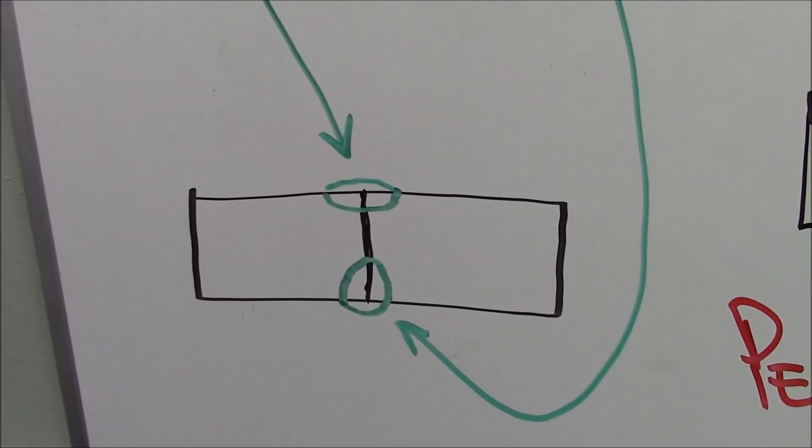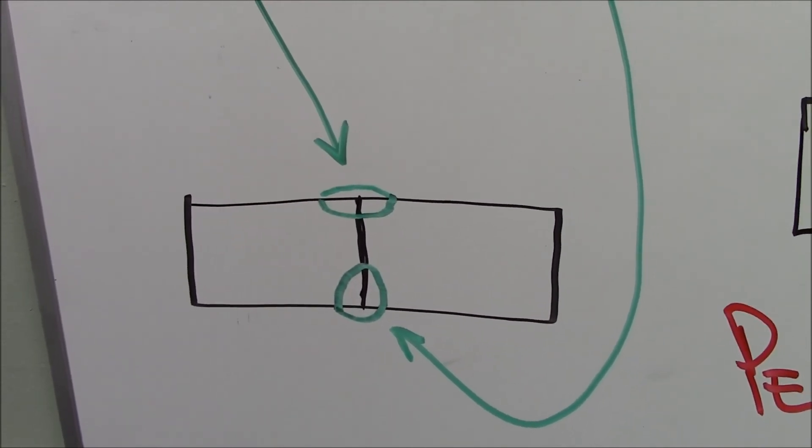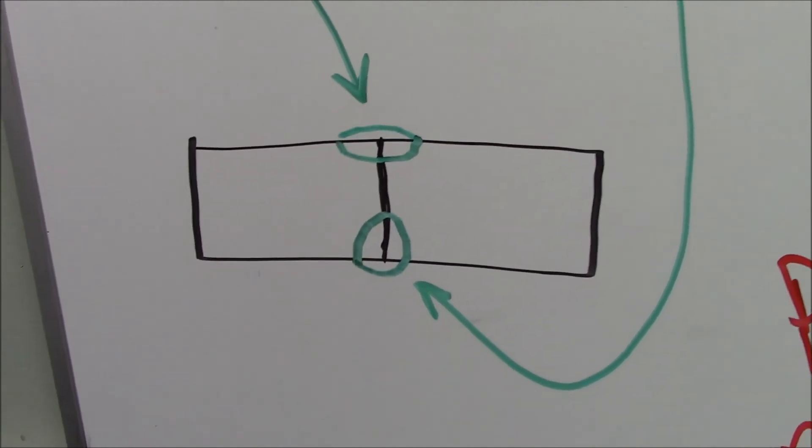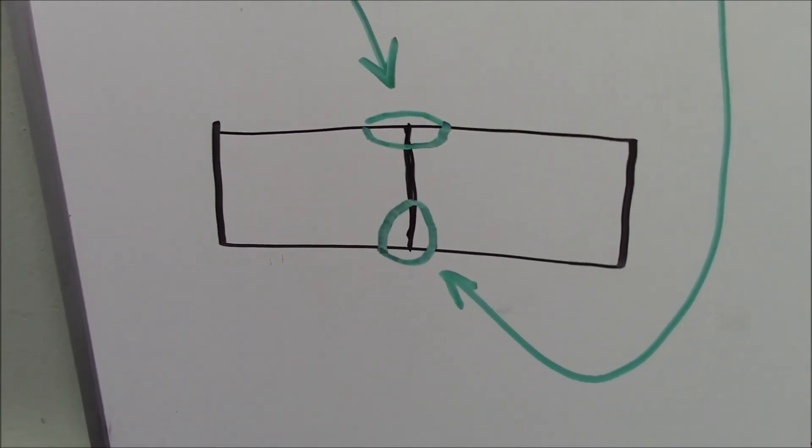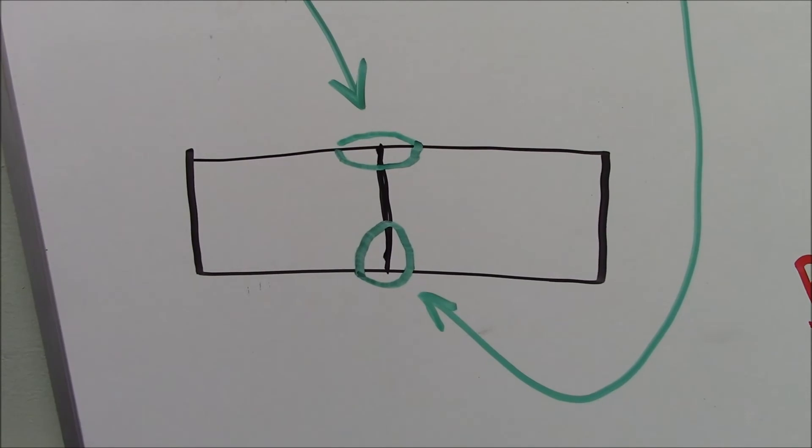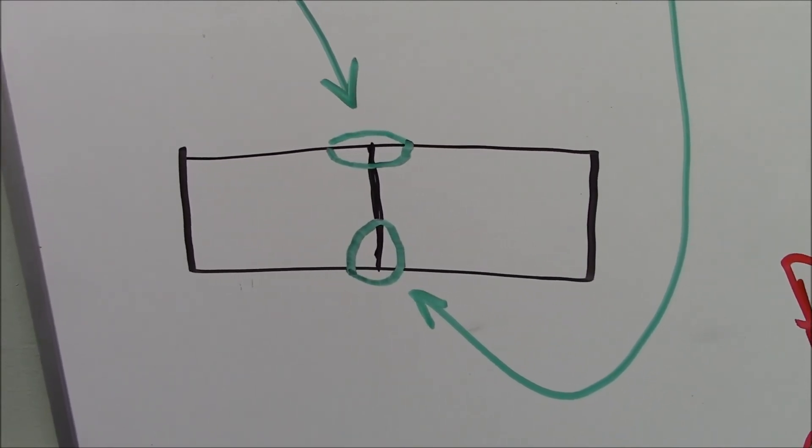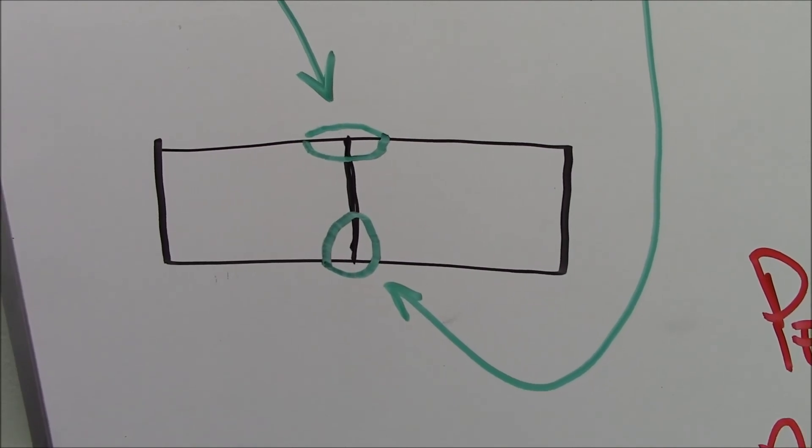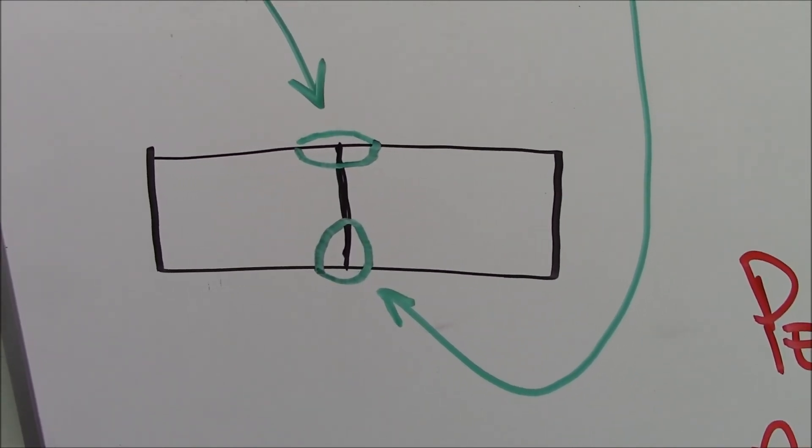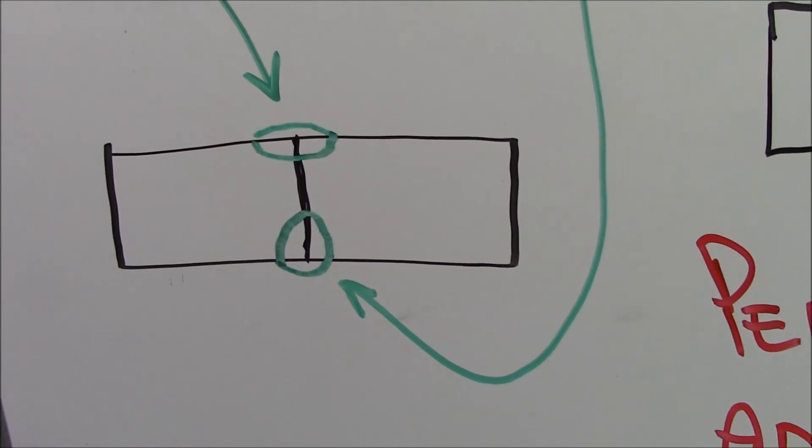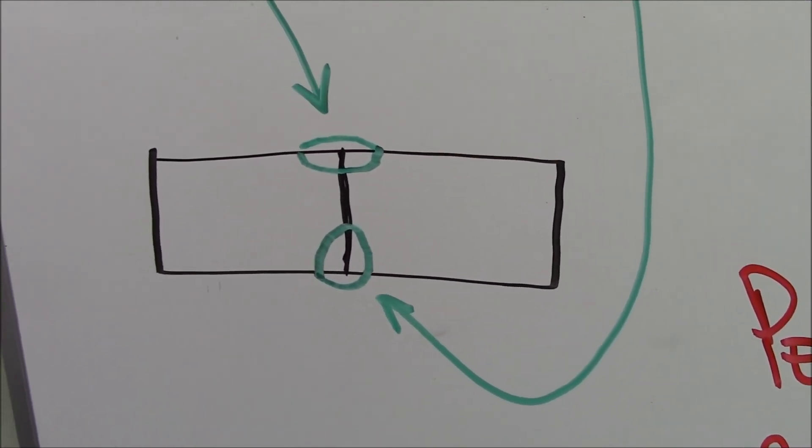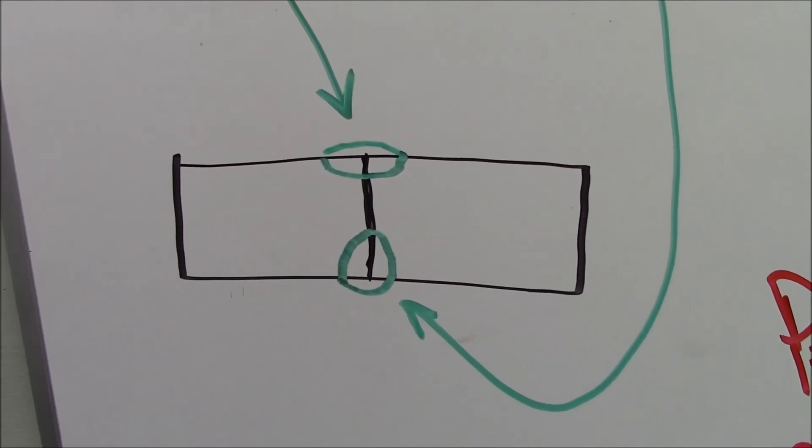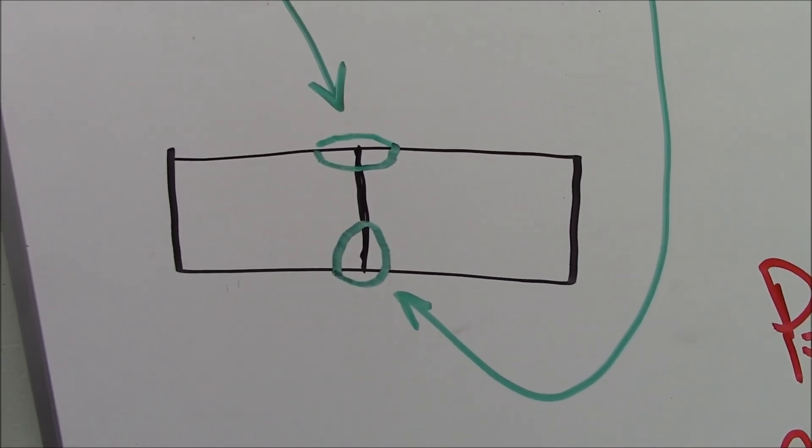like the chemical composition from the base metal. So, if you want to take those characteristics more than the filler metal, then you would want a square groove weld. And that way, the majority, like approximately 70% of the composition of the weld is the base metal and then 30% is the filler material. Whereas, if you would have a V groove, then it's kind of flip side that and you have 70% or maybe 80% filler material and 20% or 30% of it is the base metal.